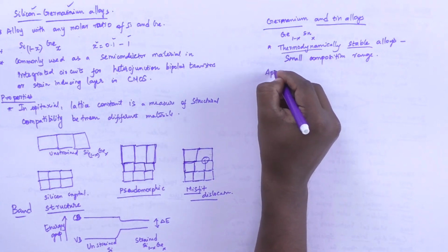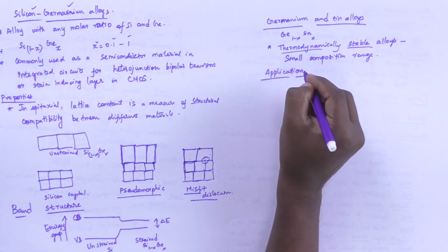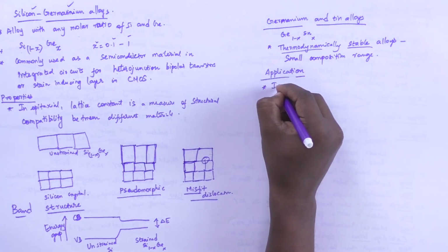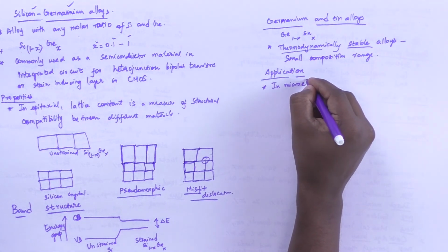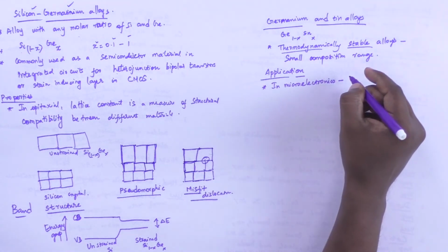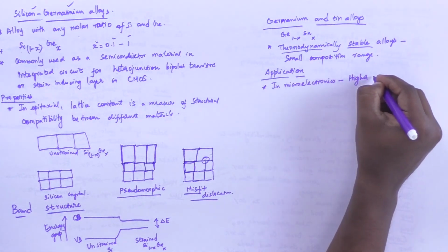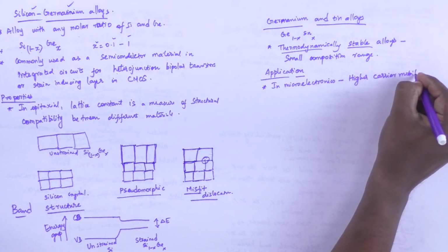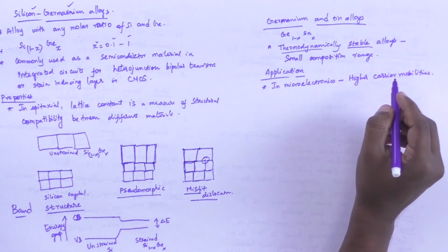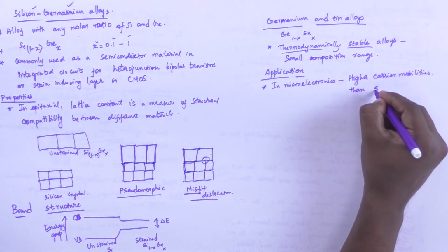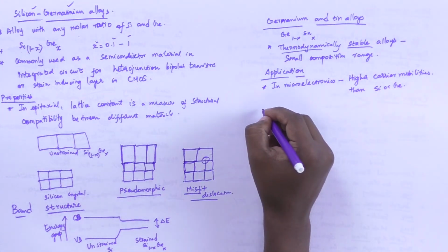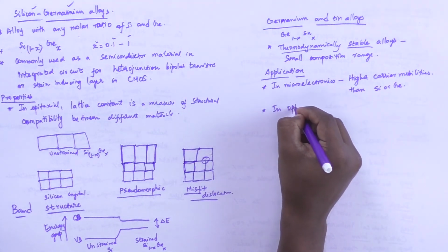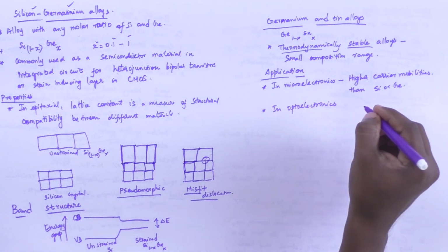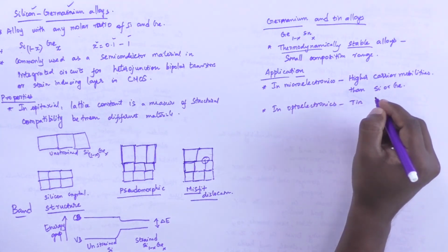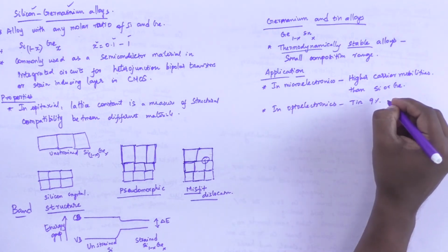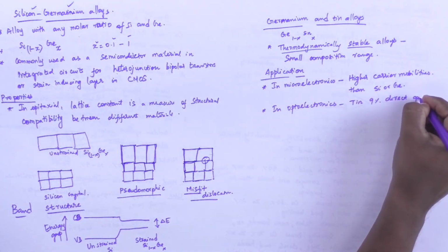And the main application of the germanium and tin alloy is in the field of microelectronics. In microelectronics, the main application is due to higher carrier mobility of these alloys compared to pure silicon or germanium semiconductors. The second case, it is used in optoelectronics, and in optoelectronics, if tin is more than 9%, it will have a direct gap semiconductor.